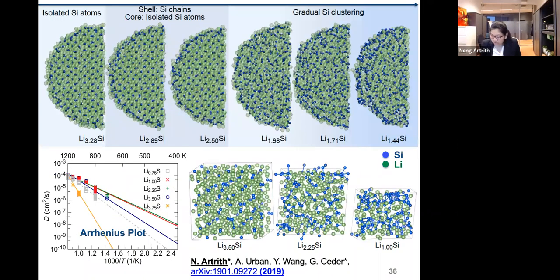Yeah, because during an MD simulation, some structures can be very close to each other, which includes high energies. So you cannot use the pure MD structure of each frame in the training set. You need to also introduce the short distance, high energy structures in the training set, because while you are running the MD simulation, at some point your structures will move very close to each other. And this is very important.